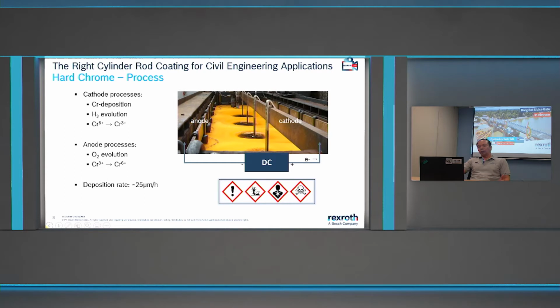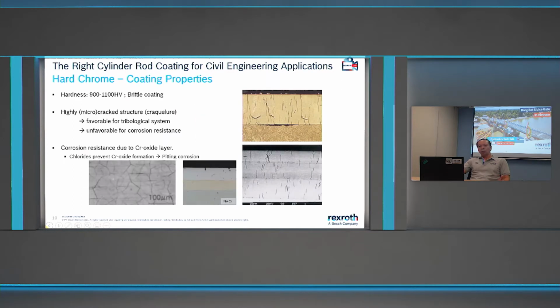So this process is a very old technology. We all learned it from school. It's the electroplating process where the chromium is deposited from the chromic acid solution, and the deposition rate is about 25 microns per hour. Due to environmental issues, such technology is no longer allowed in some European countries. Using this coating technology, we have a high hardness from 900 to 1100 HV. It's hard but liable to break easily.